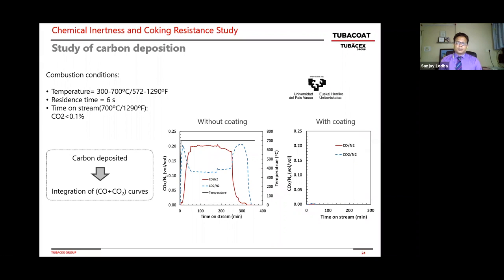Then once you make the carbon, again, where does the carbon stay? Does it deposit on the tube surface or not? So what we do in this experiment is burn the carbon through an oxidation process and integrate the CO2 chromatograph curves. Again, on the surface without coating, you can see very high CO2 curves over a significant period of time, over 400 minutes, 360 minutes. But with the coating, there are no CO2 curves and it goes away within 60 minutes, reconfirming the carbon deposition is very, very low on the coated surface. Next slide.